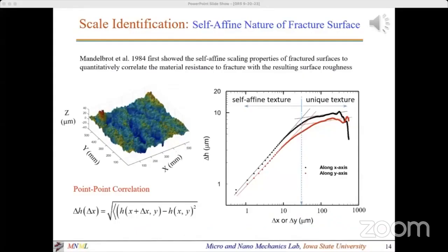Mandelbrot et al. in 1984 first showed the self-affine scaling properties of fracture surfaces to quantitatively correlate the material resistance to fracture with the resulting surface roughness. So, I am here to show a topography image acquired by 3D microscopy, and to the right, I am showing a statistical measure called height-height correlation. It's scaled with the analysis window delta x, indicating self-affine behavior.